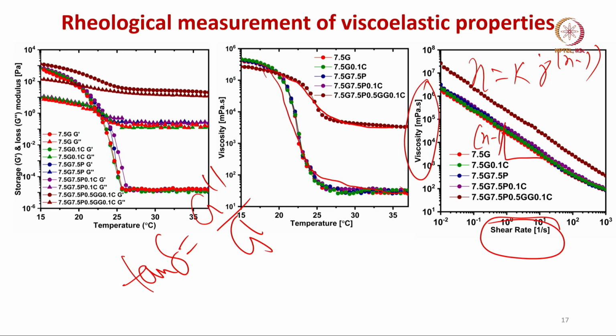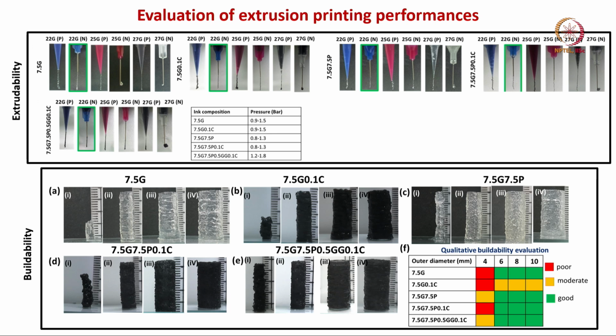So, this was important, and you also have to note what is the temperature window in which this particular gel is to be printed. It should be somewhere between 20 and 25 degrees Celsius, because at 20-25 degrees Celsius, you can see viscosity also drops very significantly with the hydrogel modifications. Now, in terms of printability or extrudability, we have used different nozzle diameters, and we have used both the plastic nozzle as well as the metallic nozzle. P stands for plastic nozzle. Now, you can clearly see that with the modifications of this 7.5% GELMA, their extrudability is very good when you use the 22G size nozzle, and not the plastic one, but the metallic one.